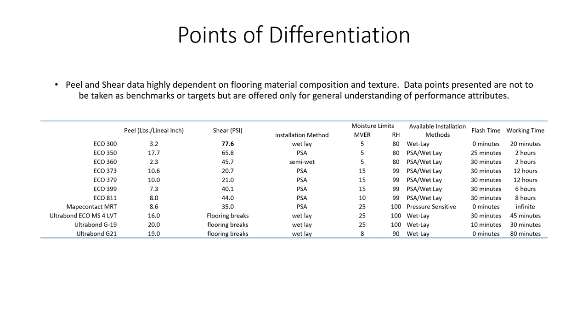They were all typically done with the same kind of vinyl flooring and the same substrate, which was cement based, but we have provided you some details here of how well they work. Eco 300, that old school wet lay hard set acrylic, will give you 3 pounds of peel, and that's where you're trying to pull something straight off the floor, like a 90 degree angle off the floor. 3.2 is not an awful lot, but flooring is not supposed to be pulled off the floor, frankly.